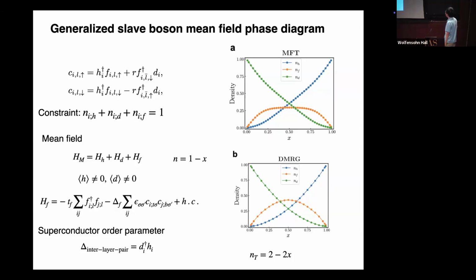If you do the calculation, you can imagine this regime is doublon dominated and this regime is holon dominated. So the doublon condensation must go like this, the holon must go like this, and in between there is superconductivity. That's how we explain the superconductor dome. And this mean field actually matches the DMRG, at least quantitatively. It's a very naive calculation, but it seems to work. In this ground state we have superconductivity, where both holon and doublon condense. So you can ask, can we have a phase with one of them condensed and the other one gapped?